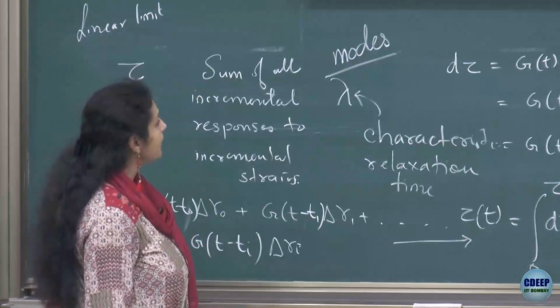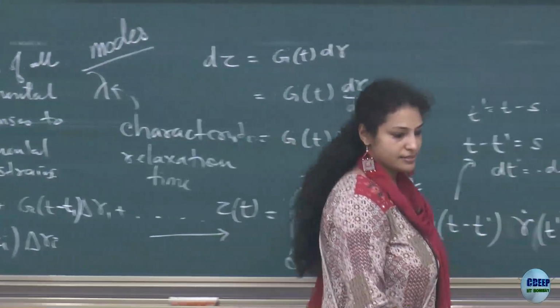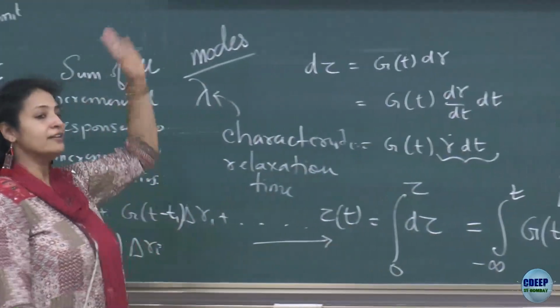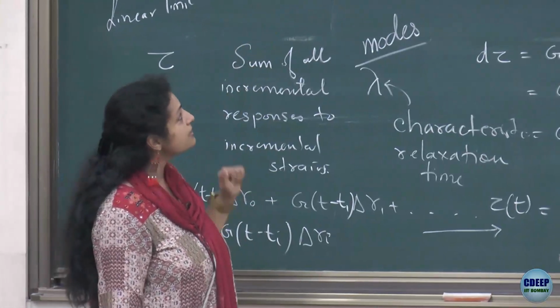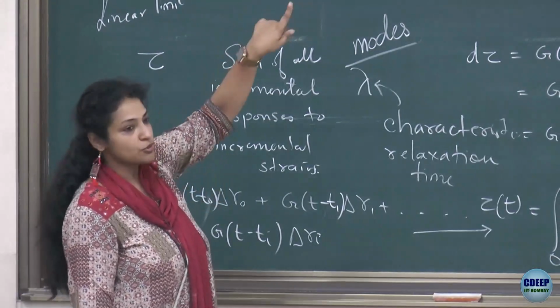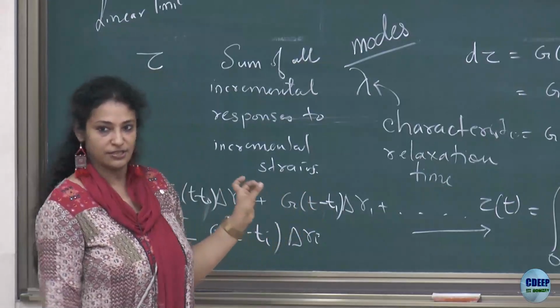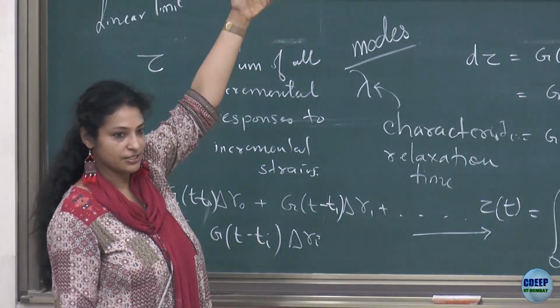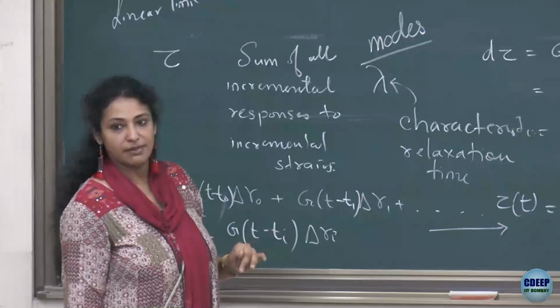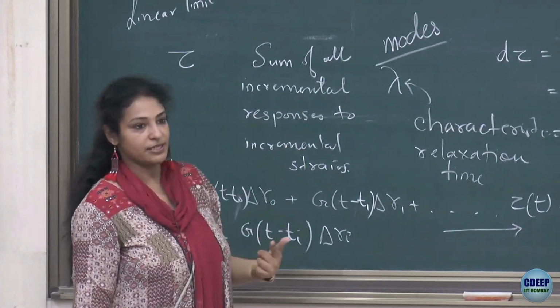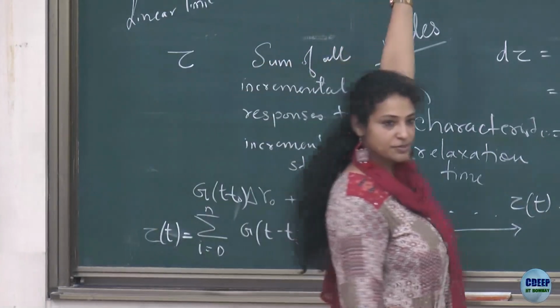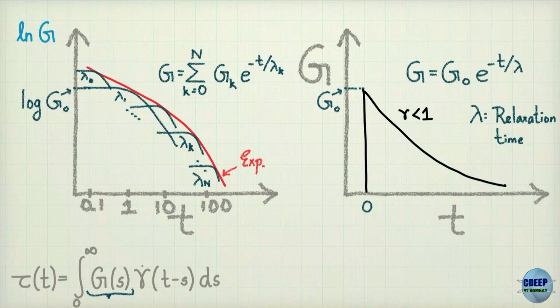Yeah. And so G would then be written as a summation of, let us say, N plus 1 modes in this case, where k goes from 0 to capital N, and each mode G of k has its modulus G naught, which was there. So you will have G naught, G1, G2, G3, G4 up to capital N, and you have exponential minus t by lambda k, where lambda k corresponds to that particular relaxation time. Right? So of course, the shortest relaxation time is going to appear on the left and the longest relaxation time is going to appear on the right. And for a graph like this, where you have a decaying modulus value, the G naughts are going to be always higher than the G k's, right, because the modulus amplitude has to keep decreasing.